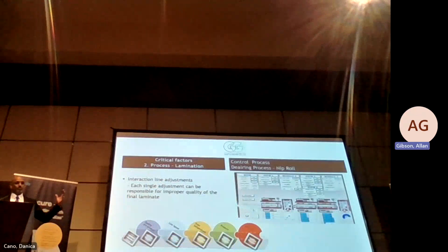De-airing process is very important. You need to remove all the air. You have 2 glasses and the layer, and then you press it and remove all the air. A little bit more amount of air that remains in the laminate will cause bubbles on the side. So each and every single adjustment that is done on this de-airing will affect the quality of your final laminate. So there are line speed, oven temperature, pressure, heaters. The heaters are now mostly convection heaters, so they are more effective. Next slide, please.